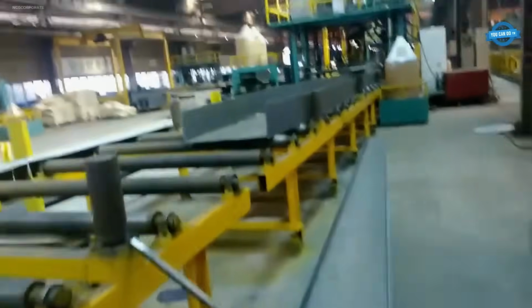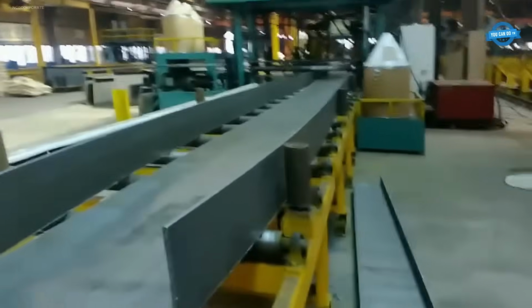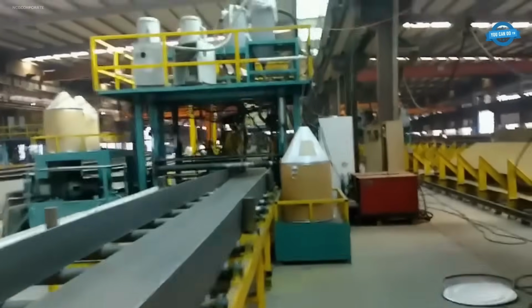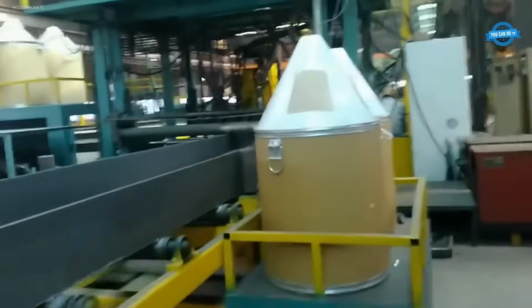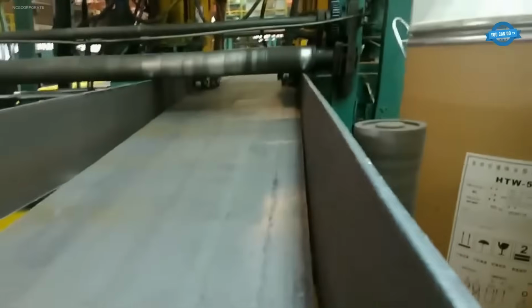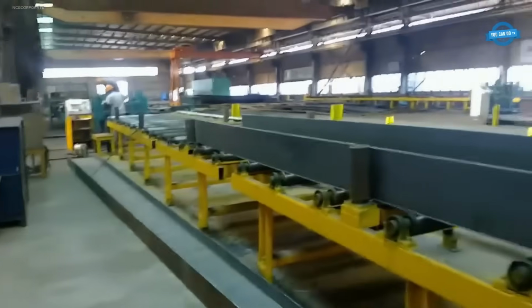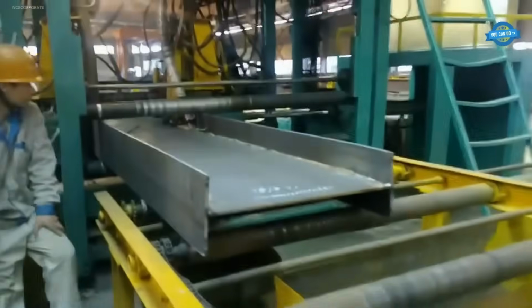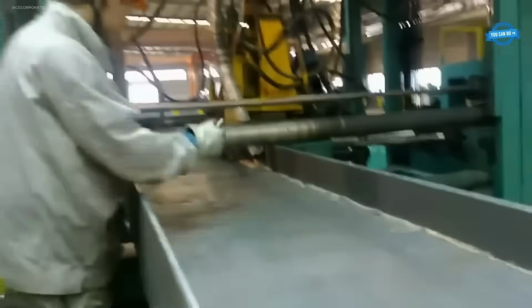Two SAW torches are mounted on a gantry system, positioned on either side of the vertical web. These torches operate simultaneously, welding both sides of the beam in a single pass. The SAW process involves a continuously fed wire electrode and a layer of granular flux, which covers the arc zone. As the arc melts the wire and base material, the flux forms a protective slag that prevents contamination and helps shape the weld bead.